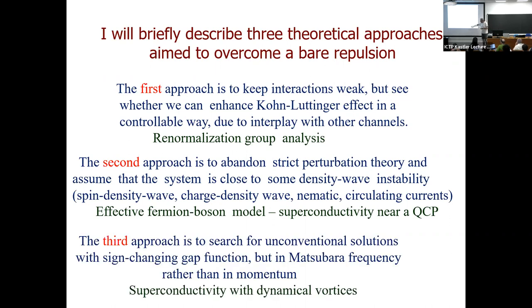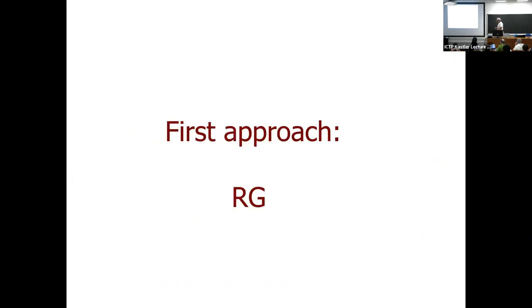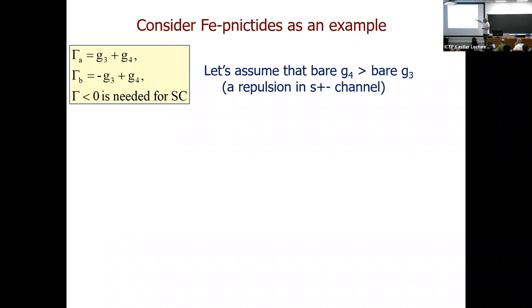And the third one, again, if I have time, will be very quick: can you get s-wave out of repulsion? The answer is you can get s-wave out of repulsion, but it will be a situation where you get a gap which changes sign as a function of frequency, and it all goes into superconductivity with embedded dynamical vortices in it. So let me tell you about the RG approach very quickly. It works best for iron-based materials.